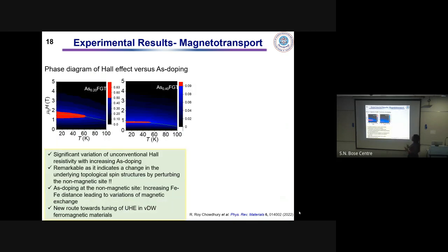And finally, we have constructed the phase diagram of the Hall effect versus arsenic doping. You can see that there is a significant variation of unconventional Hall resistivity with increasing arsenic doping. This is remarkable because it indicates a change in the underlying topological spin structures by perturbing the non-magnetic site also. Till now, there was no report of a change in the spin textures even by doping at the non-magnetic site.